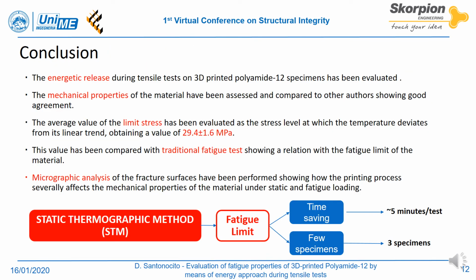In this work, the energetic release during tensile tests on 3D-printed Polyamide-12 specimens has been evaluated. The mechanical properties of the material have been assessed and compared to the authors' and data sheet values, showing good agreement. During the same tensile test, the infrared camera allowed the application of the static thermographic method, monitoring the specimen surface temperature. The average value of the limit stress has been evaluated as the stress level at which the temperature deviates from its linear trend, obtaining a value of 29.4 ± 1.6 megapascal. This value has been compared with traditional fatigue tests, showing a relation with the fatigue limit of the material. Micrographic analysis of the fracture surfaces has been performed, showing how the printing process severely affects the mechanical properties of the material under static and fatigue loading.